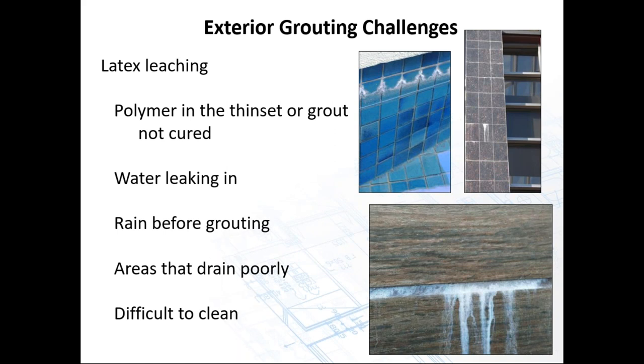The other problem that we run into where we see latex leaching is bad detailing on flashing. As a tile installer, as an architect, as a contractor, when we get together and start looking at doing a veneer, having all the trades that are going to be involved looking at this: who's doing the flashing? Is it the sheet metal guy? Is it the roofing guy? Making sure that once the tile goes up, the flashing is coming in immediately, protecting that work. So in case it does rain, moisture is not getting in behind the work and causing this latex leaching.